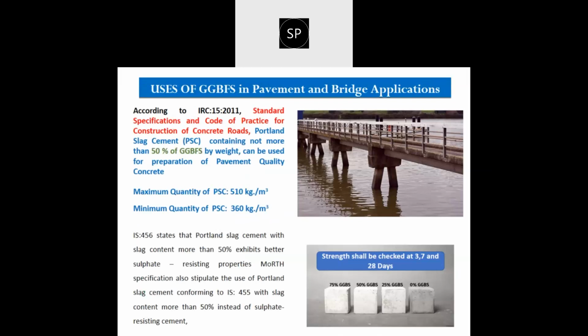So according to IRC 15:2011, the standard specification and code of practice for concrete roads, Portland slag cement containing not more than 50% of GGBFS by weight can be used for the preparation of pavement quality concrete. So the major composition in Portland slag cement is the GGBFS, but its upper limit is restricted to 50%. So any PSC which you intend to utilize should not have a GGBFS content of more than 50%.